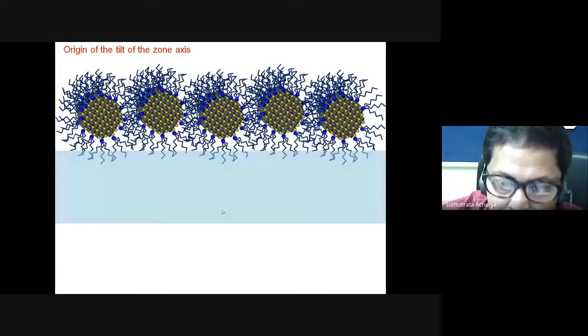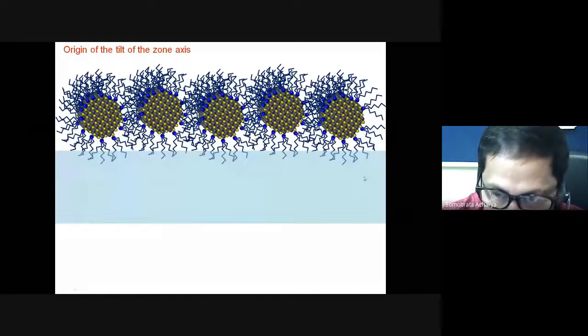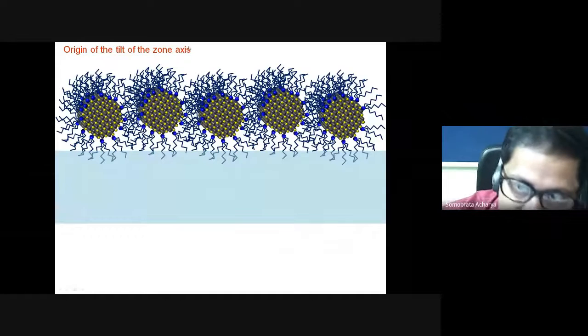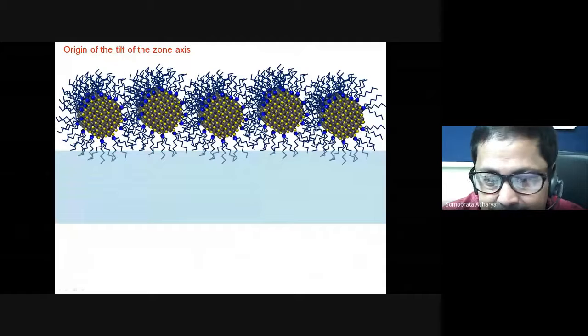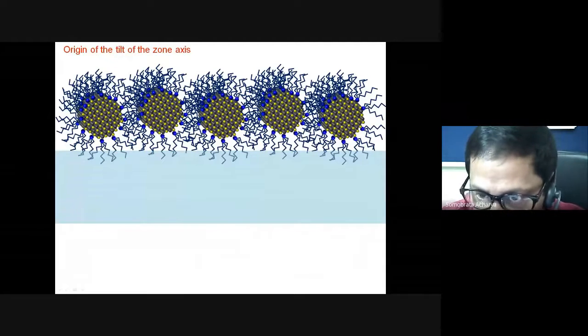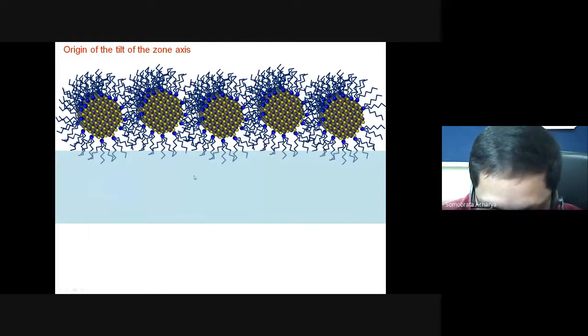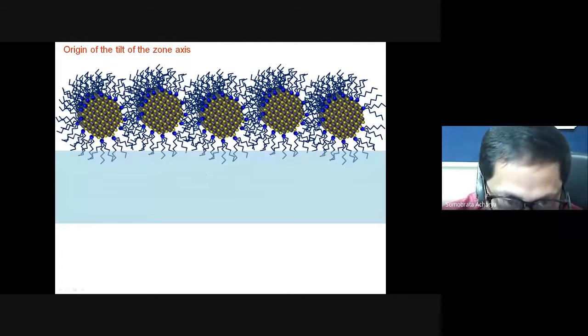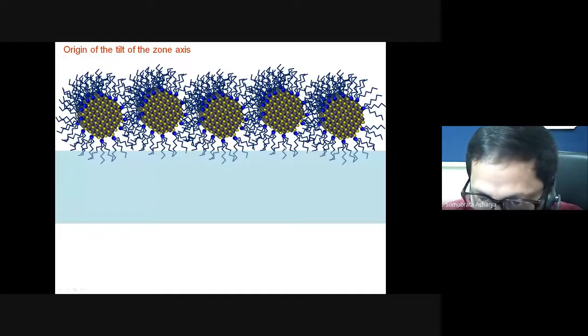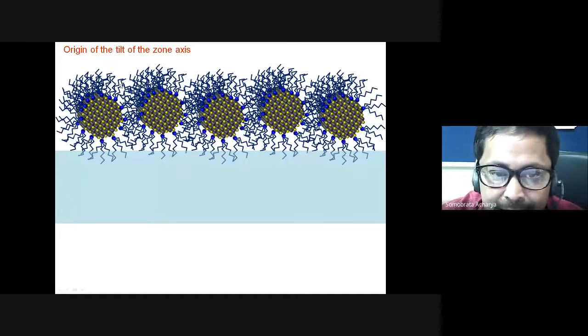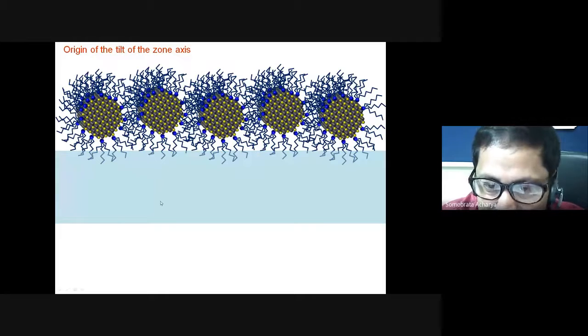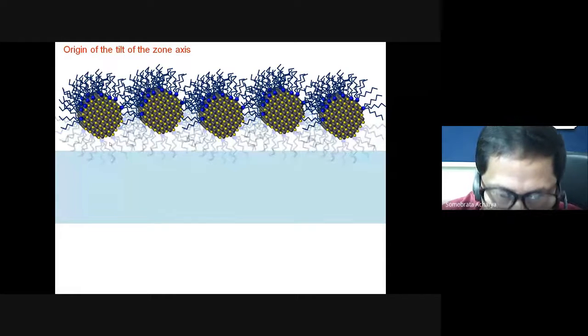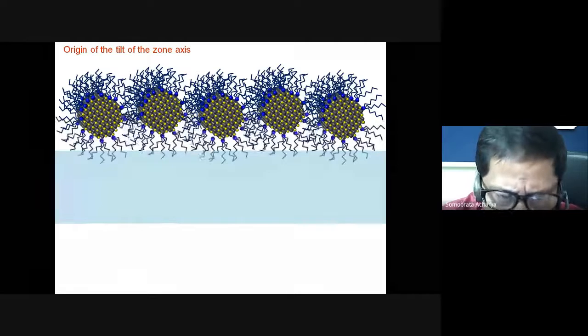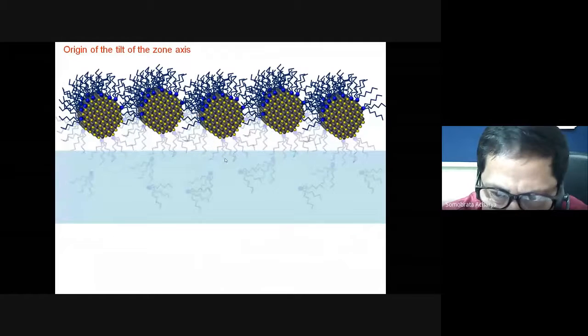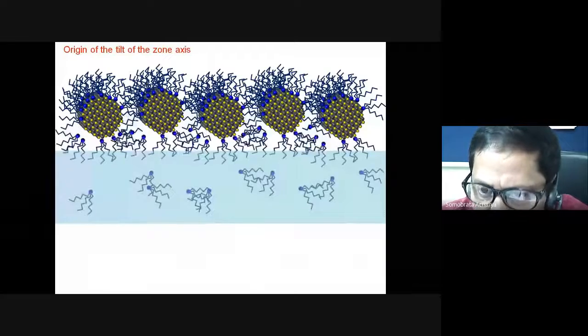Why does it tilt? Because say this is your water surface and these are the nanowires you are seeing from the cross-sectional view. Actually the nanowires are extending along this direction, and these are the surfactants or ligands that are coated at the surface of these nanowires. So once you are hitting this water surface, what will happen? The bottom ligands will be heated at first, but the top ligands won't be feeling any kind of heat. So as a result, once you are giving some energy in the form of heat to the bottom ligands, they will be dislodged from the surfaces, but the upper surfaces will remain intact.